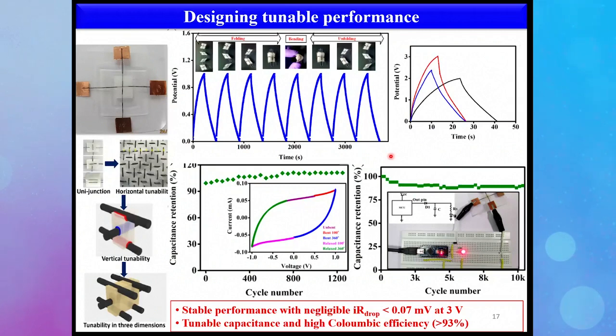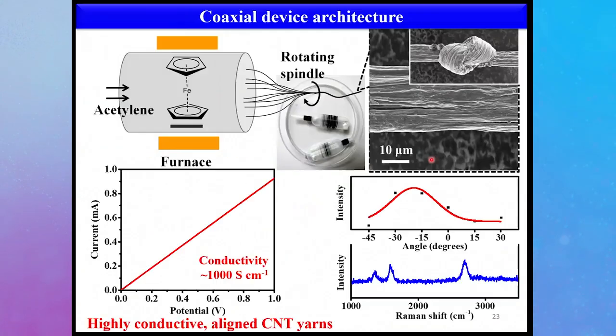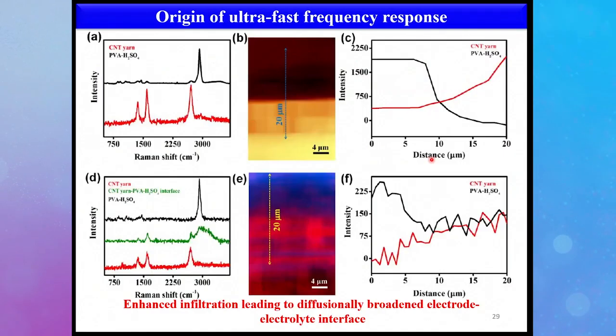Anonymous asks what does annealing do to the yarn that makes it more supercapacitive? We have done a lot of experiments. I was unfortunately not able to elaborate much on this. One of the things which I showed you is the Raman spectral mapping. Basically, the annealing helps to create that diffuse layer of the interface. If you see, there are two distinct components, one pertaining to the CNT, another the electrolyte, before the annealing. The same junction, once you anneal it, you see that now the electrolyte has infiltrated the electrode. That means you are establishing more of the electrode-electrolyte interfacial area, and that is important, and that is why the capacitive nature increases and the scan rate capability increases.